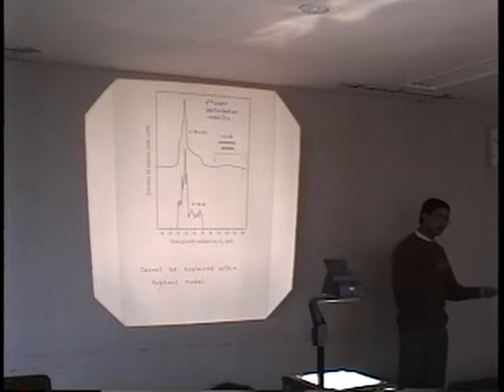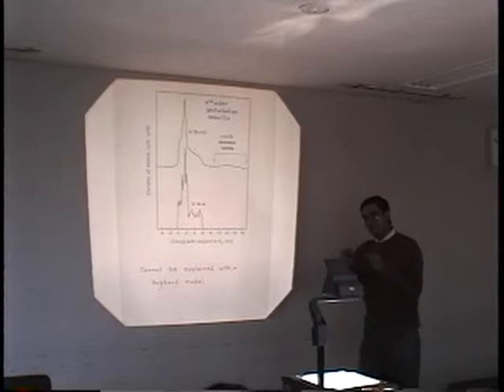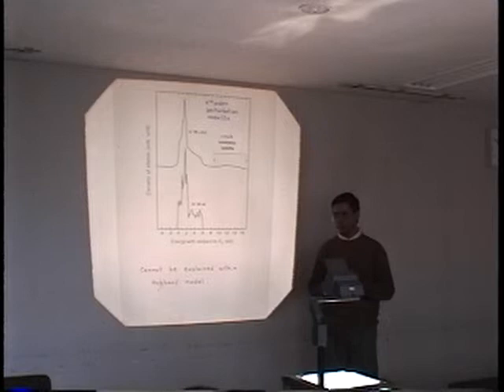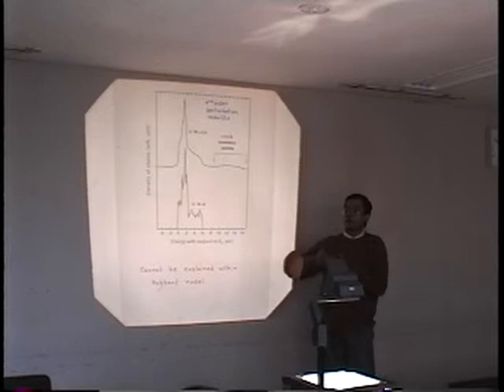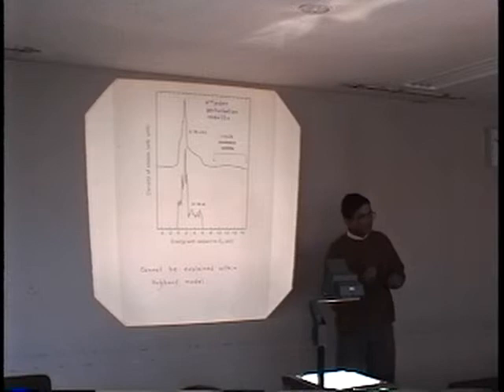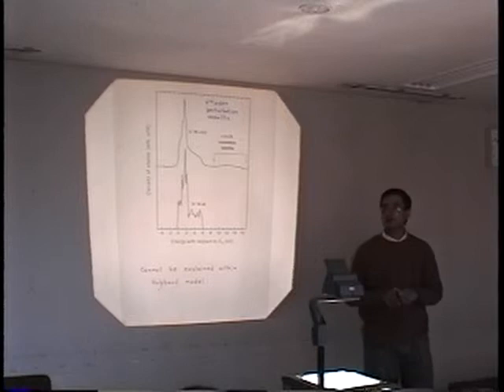So basically, you are tampering with the lattice. And you are introducing inhomogeneity into the lattice, or disorder into the lattice. Because lattice is no more exactly periodic, translational invariance does not remain anymore when you have made this chemical substitution. So you introduce inhomogeneities. What is the consequence of this inhomogeneity?